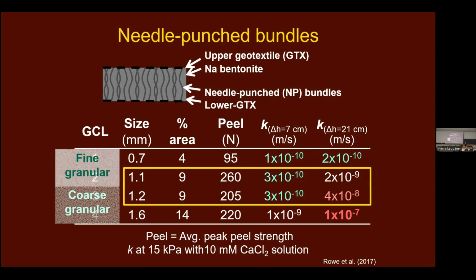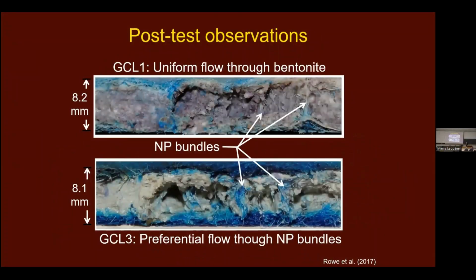These 2 have essentially identical needle punching, but when you get to 21 centimeters, you've got a substantial difference in hydraulic conductivity. And why is that? Why are we getting such high values? It's not because it's going through the bentonite, it's because it's going through the fiber bundles.